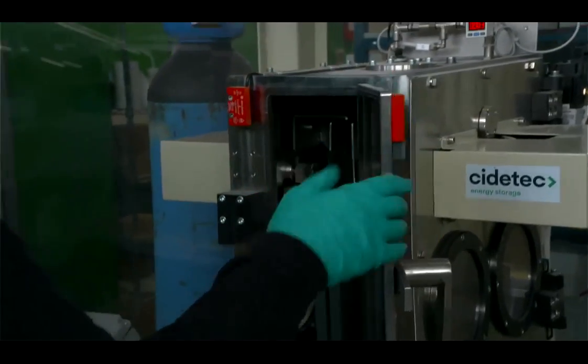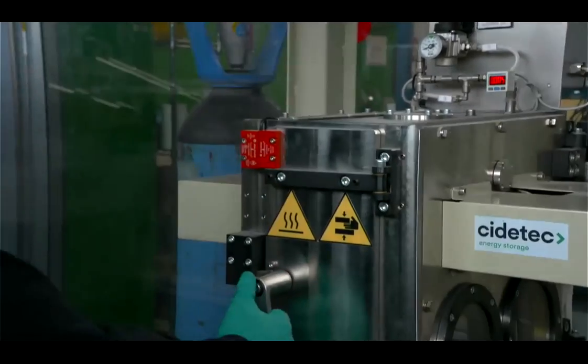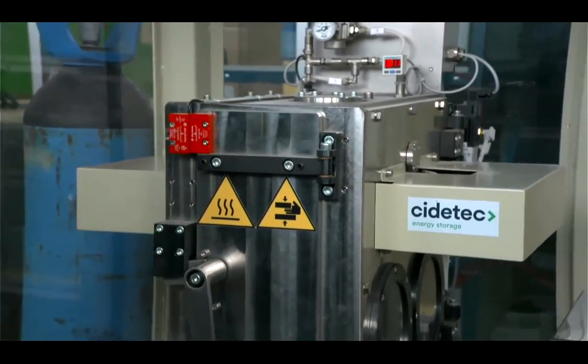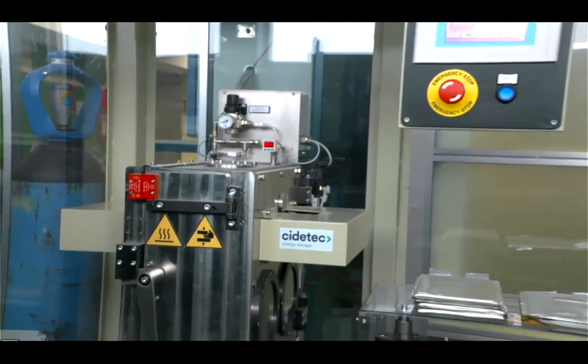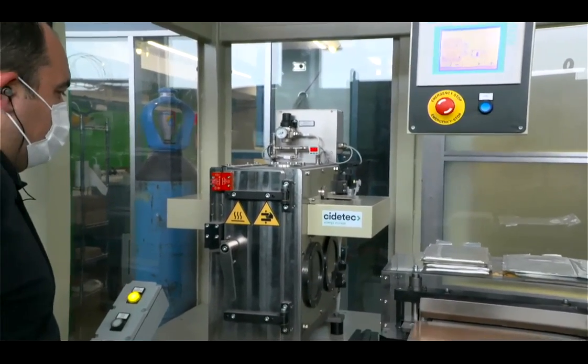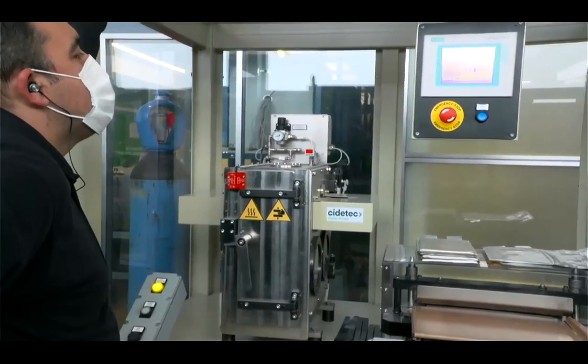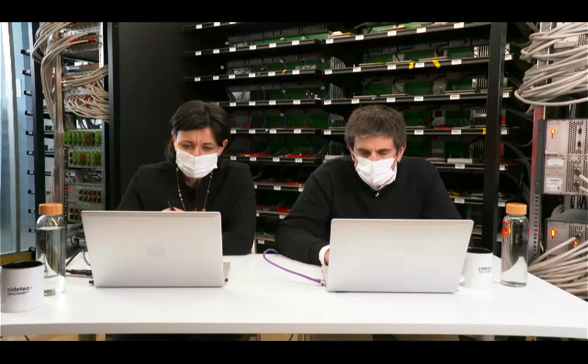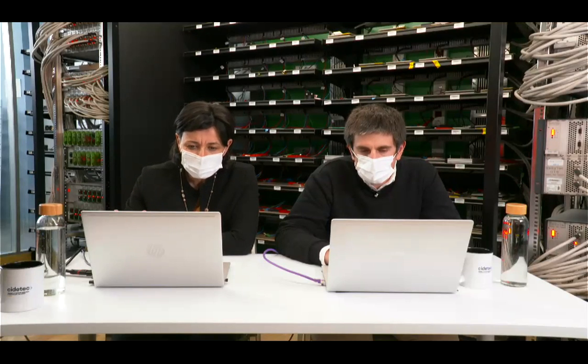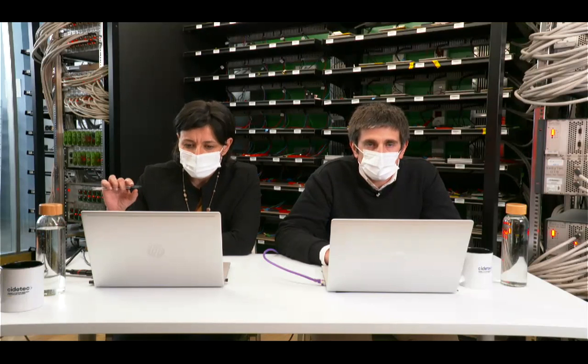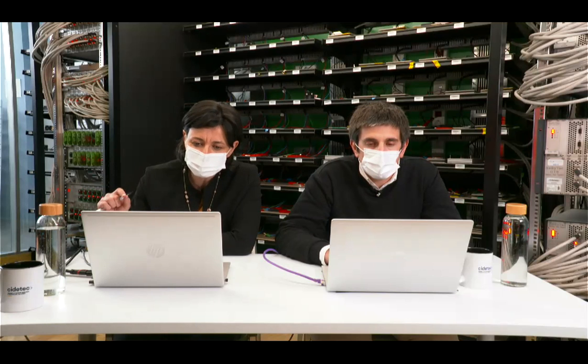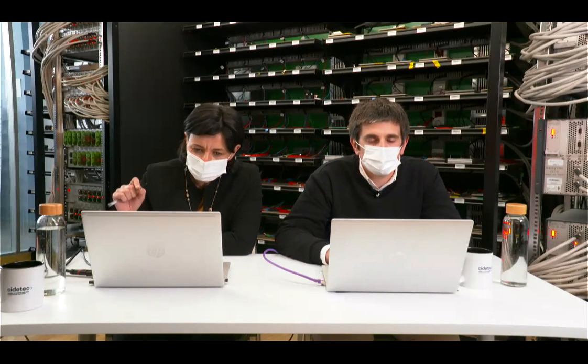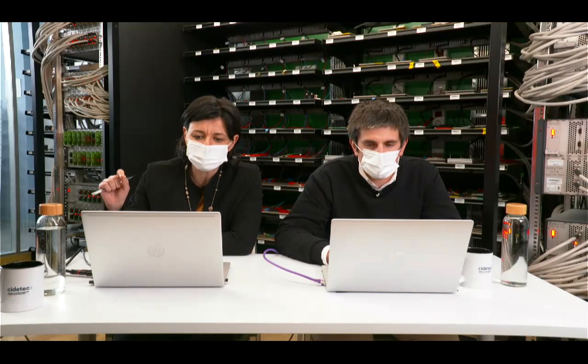Actually, this drying step inside the dry room is crucial for us because, as you have seen, all the processes are done in ambient conditions. So we really have to make sure that we dry the stack very, very well. For that, we have the Karl Fischer. We know the maximum water quantity that is allowed in the electrode. So we will be changing the temperature and the vacuum of the oven until we reach this maximum of water that is allowed in the electrode.